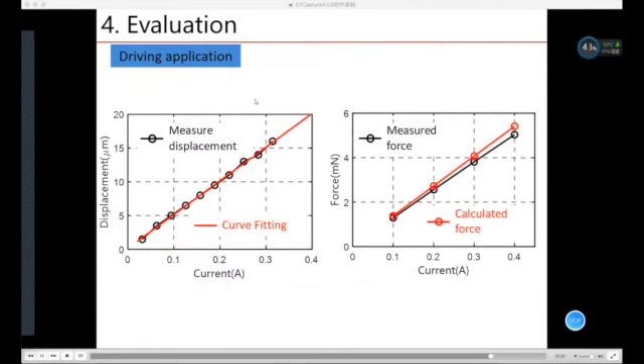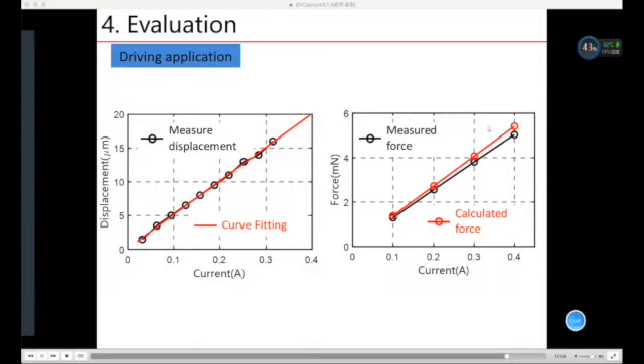This is the result. First, we input different currents into the actuator, and then we measure the displacement. We find that it fits well with the linear relationship. By using this, we calculate the force by using the stiffness from the previous slide. And then the calculated force and the measured force are compared in this figure. We find they coincide well, indicating the usability of this actuator.